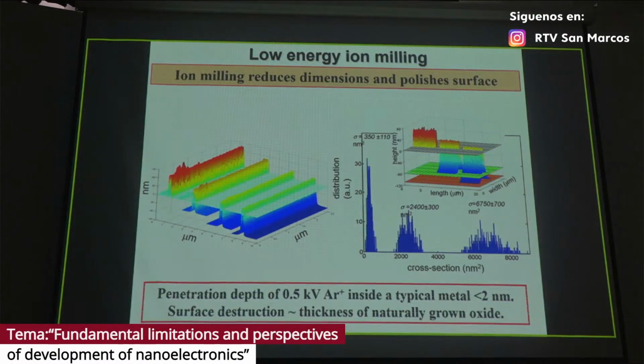And these are the AFM images of a metallic nanowire on top of an insulating substrate. Everything which is a bright color here is metal, let's say aluminum. Everything which is blue is silicon. After several sessions of ion milling, you see the cross-section of the nanowire is reduced. And in addition, the inevitable bumps, which you can see here, for example, are disappearing. Typically, I'm asked whether the method is invasive or not invasive. Everything depends on the acceleration voltage you apply in your ion gun. If it is rather small, let's say below 1 kilovolt, the penetration depth of inert gas atoms inside the matrix is very small. It's below 2 nanometers, which is comparable to the chemically damaged surface. So from this point of view, the method of reduction of the dimensions is non-invasive.